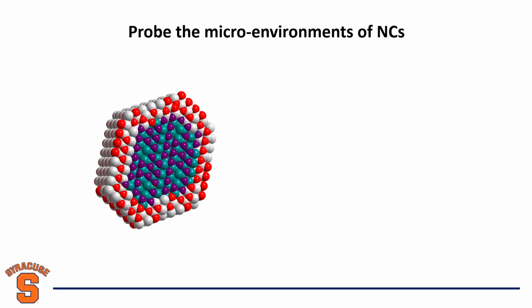And we know surface atoms and the atoms inside have a way different chemical environment. For example, atoms inside the particles form more bonds, highly saturated. Atoms on the surface form fewer bonds. For example, if I'm a certain atom looking down, I find a neighbor, looking up, empty. The atom inside the material looks around and sees all neighbors. So surface atoms form fewer chemical bonds and are more reactive, because bond formation is an exothermic process, releasing energy, right? Form fewer bonds, more reactive. That's why we can use small particles, with surface atoms, for catalytic reactions. Okay, so this is a theoretical model for 1 nanometer quantum dots. If you count how many atoms are on the surface, it is more than 30%.